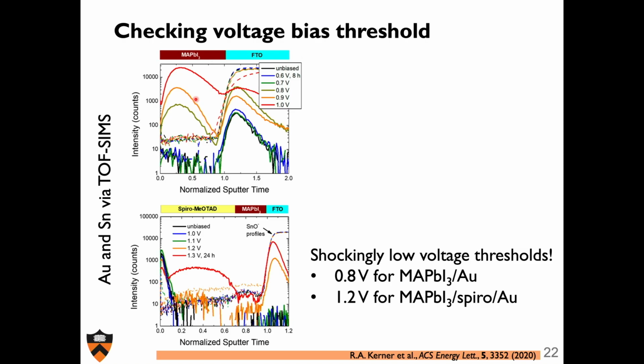So what I'm showing here are, a little hard to read, cross-sectional TOF-SIMS, I don't know what you call them, spectrograms, I guess. Depth profiles, thank you, Tonio. So what I'm looking at here is the profile for gold, as well as, in the dashed lines, the profile for tin, which is showing me where the FTO perovskite interface is. That's what the dashed ones are. And so for the gold, what we see is that at 0.6 volts, 0.7 volts, it's not enough to have any gold in the system. There's basically no gold. And then at some point, I've effectively pile-driven the gold to that gold FTO interface. But this was just the remnant of what we had neglected to get off when we peeled off the gold contact. And so you see some gold that shows up here.